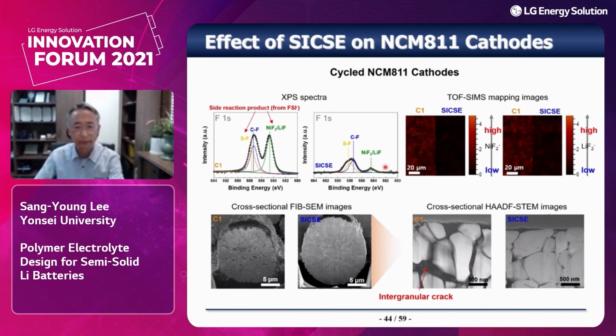which was confirmed by the TOF-SIMS mapping image. Okay, side reaction was significantly eliminated in our case. And then as additional evidence, we have examined the cross-sectional FIB-SEM image. So in the control sample, the particles were disintegrated, structurally disrupted. By comparison, in our case, as you can see, the NCM811 particles can maintain their structural integrity.